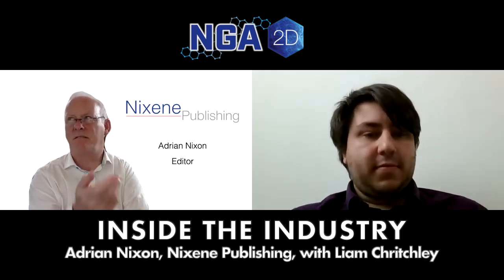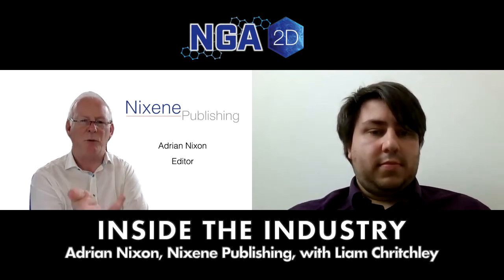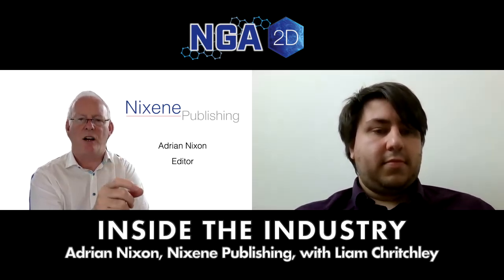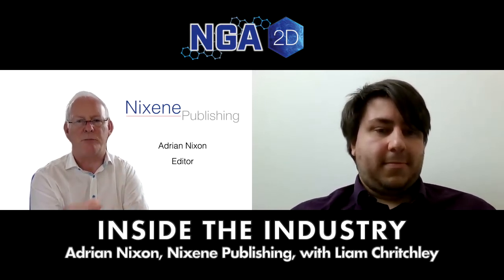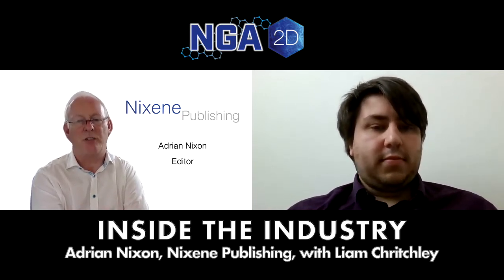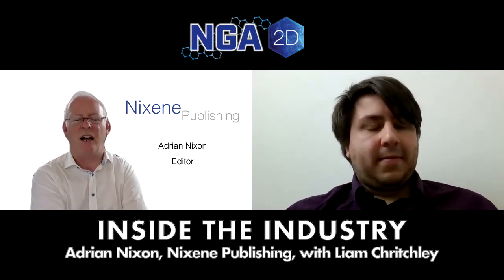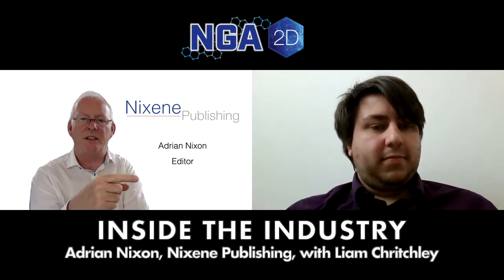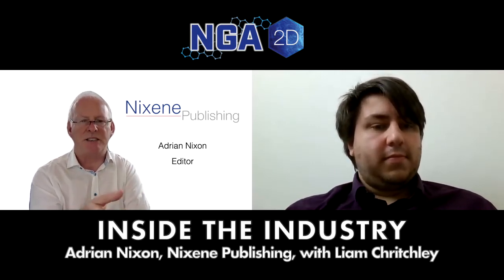So again, Liam, you're familiar with this. Maybe the viewers, we'll probably have a mixed audience, so I'll just expand on that a little bit. You put a tiny amount of graphene into concrete, so this is going to be 0.01% by weight, and you increase the compressive strength of the concrete by 25%. It's absolutely insane. Yeah. Tiny amount has a massive, more than double digit improvement. And what that means is that concrete and cement manufacture accounts for something like 8% of global CO2 emissions.